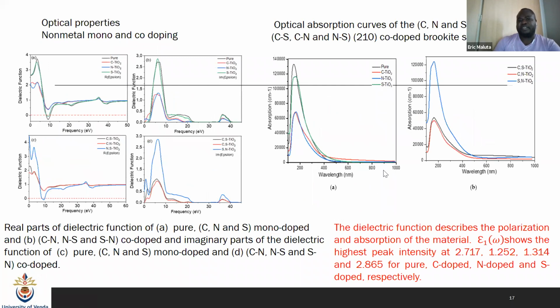We also look at the optical absorption curve of non-metal doping, and we can see the same similar trend: our pure surface absorption is improved to the other side, as I'm moving the cursor here to show. Looking at the pure one, which is the black one, which dies around here, the (210) surface, when we do the doping, we can see that we are improving the absorption even towards the near infrared. And then what we also look at is the dielectric function, as it describes the polarization and absorption of the material, to see what is really happening.